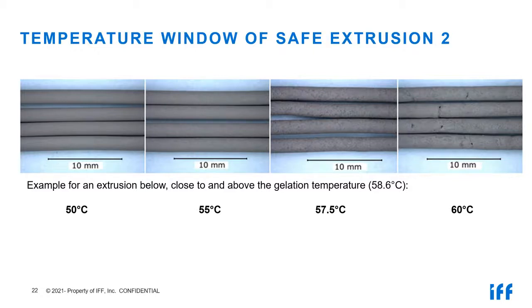The profile looks very well, no holes, a very smooth surface, everything is okay. But then 5 degrees higher, in the second picture, you can see the surface shows already a slight cloudiness. The profile is still even and looks still okay, but you will realize that first micro defects occur, but maybe you can still sell this material. You should make a test after sintering.